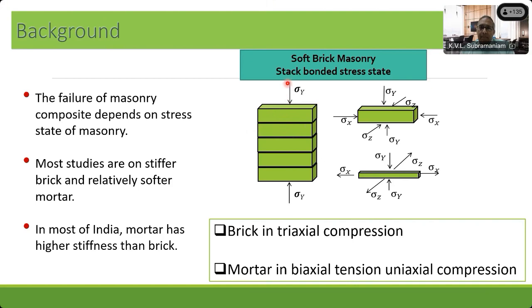So what happens then? When I apply a compressive stress on this, the brick doesn't expand as much. The expansion comes about because of the lateral expansion, which we associate with the Poisson's effect. Because the brick is stiff, it doesn't compress as much and it does not expand as much. Whereas the mortar, when you're talking about stiff brick masonry, is actually softer than the brick, which means that the mortar would compress more and would also expand more in the lateral directions.